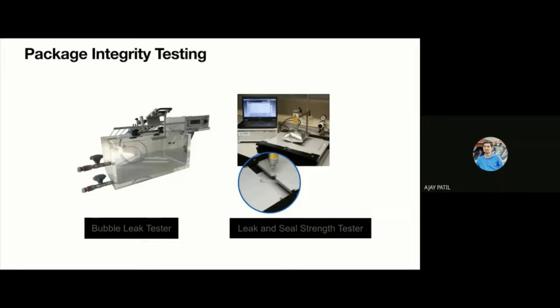Another very important test is leak and seal strength test, which can be carried out in creep mode as well as in burst mode. Now, all of these put together can give you vital information about the running conditions. Were the sealer jaws maintained properly? Was the pressure in the jaws maintained properly? Was the temperature in the jaws maintained properly? Because in the end, if you have the perfect barrier, you have perfect inertness in the packaging, but the machine was not set up well to run the package, then the package is going to fail.